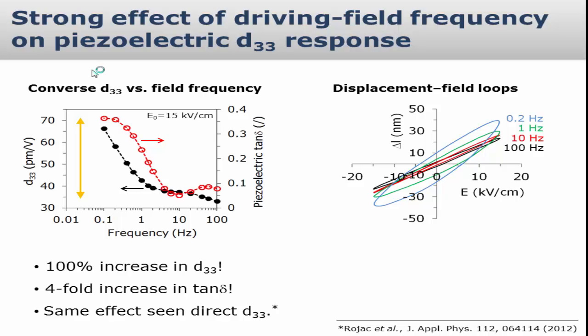So this is the piezoelectric coefficient as a function of frequency. The converse one was measured with a fiber optic sensor as a function of frequency. The main point, the particular thing in the response of bismuth ferrite, is that it has a very strong frequency dispersion above 1 Hz. For example, D33 jumps by a factor of 2, and then you have this piezoelectric phase angle, which is the phase angle between the strain and electric field response, sinusoidal ones, that is getting very high, by a factor of 4. This is different, for example, from PZT and many other materials, something similar to lead titanate, but I will show you it's a bit different. And this gives this loss in piezoelectric loops at very low frequencies.